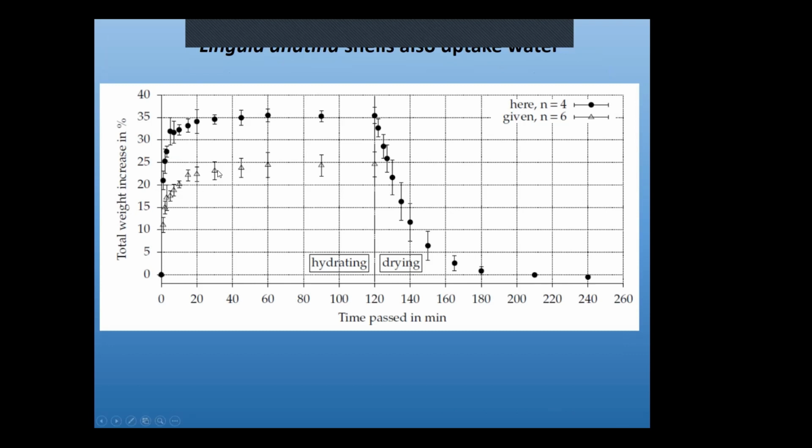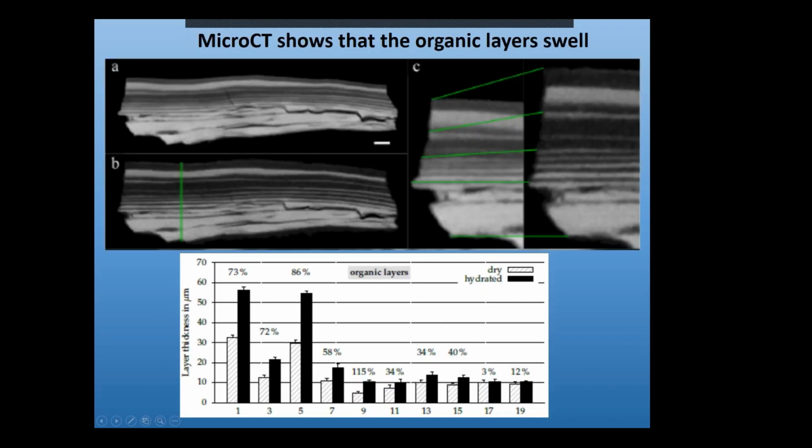And we see that the water absorption increases. The shell absorbs about 25 to 35% in weight water, so it does take quite a lot of water. And that takes about 20 minutes for the material to be saturated. And that was a neat experiment that we did.